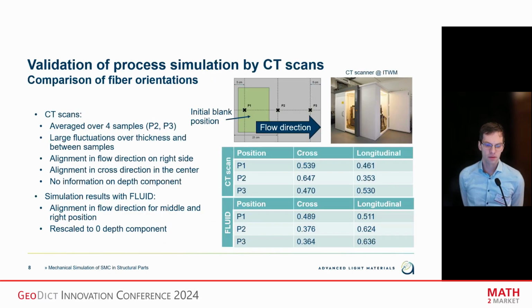Then we did some validation by CT scans. CT scans in this respect are a bit of a difficult task because the fibers are so long and the bundles are so large, and still you need to resolve their structure somehow by the CT scan. So usually the CT scans are too small to really give a good impression of the fiber orientation. What we did is we averaged a larger number of CT scans to obtain some meaningful values and performed this at 3 different positions over the plate and compared this to the fiber orientation we obtained from the simulation.